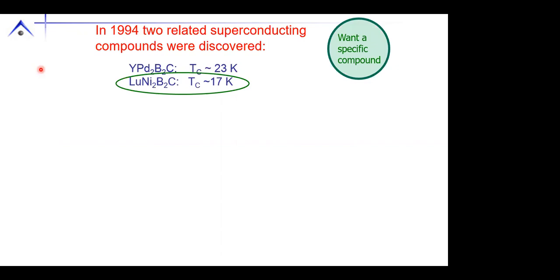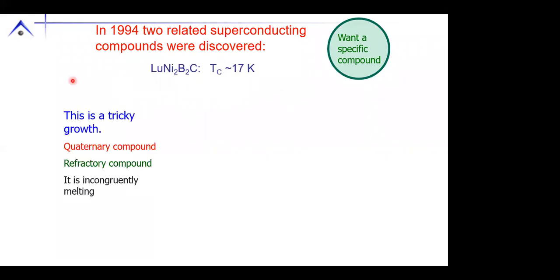So at the time, we really wanted to grow the lutetium nickel boron carbide because this was stable as opposed to metastable. Now, it's a tricky growth. It's a quaternary. It's refractory, it's incongruently melting. All we were missing was toxic and radioactive for the full 5-fold don't try this at home category. But these we could manage.